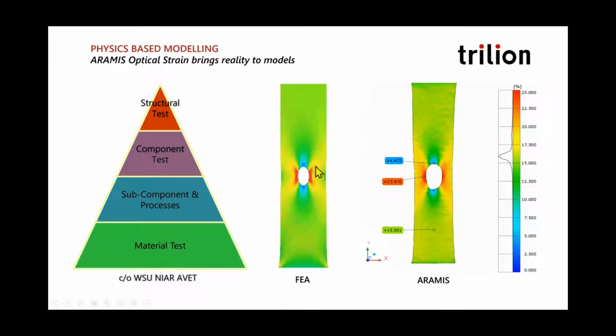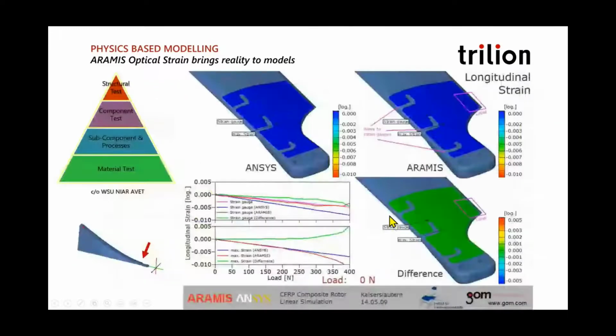When you get into material testing, we like the finite element model. It looks beautiful. And we say, well, you know, the Aramis really should be a little bit better to match the model. Actually, it's the other way around. These local variations are the true variations in the material. And the Boeing modelers say, we need your experimental data to really get our models to match reality.